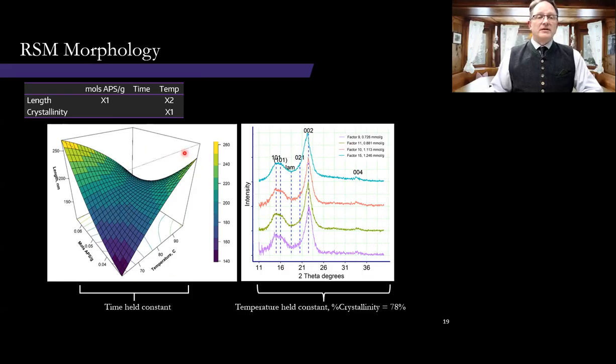The 3D surface plot here, again, same thing. We can hold time constant since it's not an effect, increase our APS, increase temperature, and see what the response is for our length. On the right, the XRD diffraction pattern here, holding temperature constant, shows that without temperature moving, we have a constant crystallinity. The patterns as surface charge changed were identical.